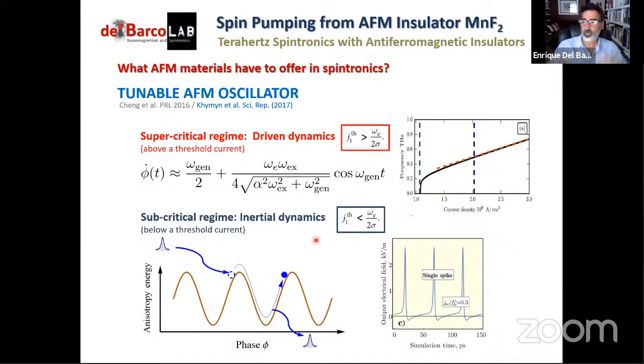So here, we don't have enough energy to give to the system to go over the barrier. But if we stay here with a DC current below the threshold, and then we send a little extra pulse of current, we'll get the system jumping, and then it will emit an electrical signal in a very, very short period of time. So it's one way of generating very fast picosecond spikes of current that may become very interesting for some applications, for example, neuromorphic computing, computation and things like that.